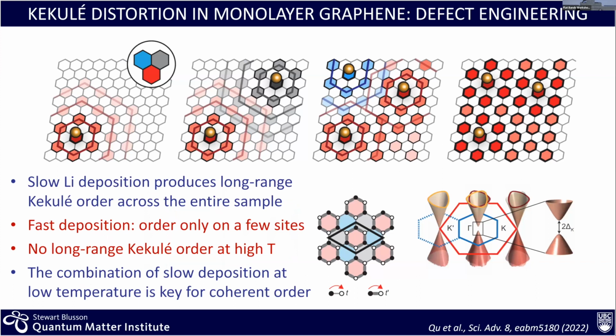Fast deposition, basically you get order only on a few sites and immediately go into a frustrated type of situation. Working at high temperature, then the mobility of a lithium atom is too high. Again, you're not able to establish a longer order. So really you need a combination of very slow deposition at temperatures which are intermediate, let's say, to be able to establish this very long coherent type of order.